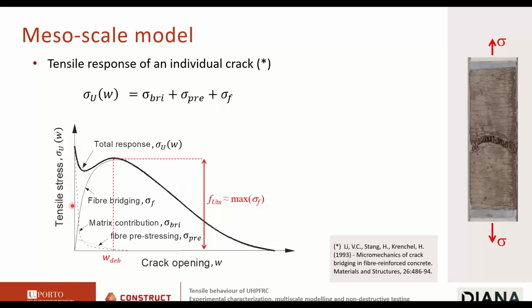Of course, there's a small contribution from the matrix, very small. And a small contribution of what is called in the literature fiber pre-stressing, which is basically the elastic stresses in the fibers locked in prior to cracking, which after cracking are gradually released. Important also to note that the fiber contribution can be divided in 2 stages. First we have a fiber activation stage, also called the fiber debonding stage, where the forces in the fiber increase. So the bond between the fiber and the matrix is being activated in this stage, and then the fibers start to pull out. The post-cracking tensile strength of the cracks is fairly given by the fiber contribution.